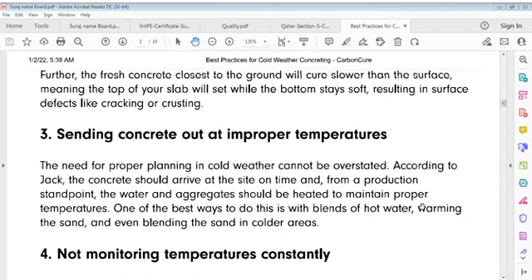Let's say sending concrete out at improper temperature. One more thing: fresh concrete closest to the ground shall cure slower than the surface, meaning the top of your slab sets while the bottom stays soft, resulting in surface defects like cracking or crusting.